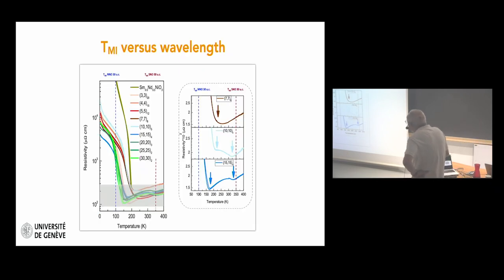So let's look at the transport properties. This is resistivity versus temperature for an entire series of superlattices with different thicknesses of each layer. And what you get is finally something which is quite reasonable. If you look here, this is a 15 unit cell sample, so quite thick layers. If the layers are quite thick, you imagine that the behavior will be the one of samarium nickelate and neodymium nickelate. And in fact, this is what you see. You see a first transition here. The samarium nickelate layers become insulating, and at lower temperature, the neodymium nickelate layers become insulating.